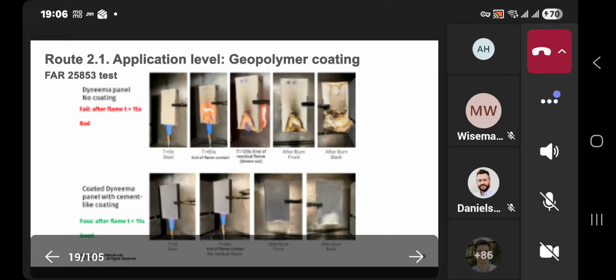This is yet another example of the approach at application level. Here we applied a geopolymer finishing coating. And you see here again two sequences of pictures, top and bottom, with the top for Dyneema without any coating. Here you see essentially that, again in this test, Dyneema without protection catches fire very quickly. There is a very long afterburning time. It needs to be blown out to put out the fire, and then you see how the panel looks at the end of the test: totally burned, destroyed, melted away. While the panel with the coating is very difficult to ignite. It doesn't ignite, and essentially nothing happens, and the mechanical integrity of this panel is preserved, and the test is passed.